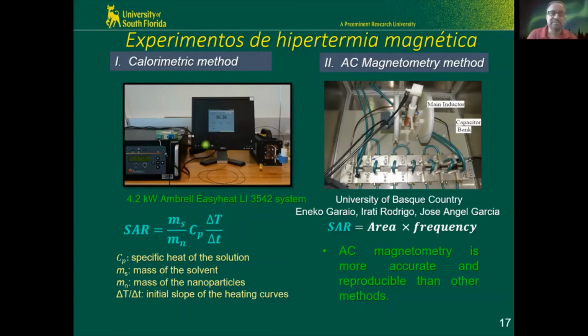And so what we do is that we measure, we have these particles in fluid or any kind of medium here, and we directly measure the temperature using various kinds of thermal sensors. It could be optical, using a laser, we can measure the local temperature. So what we measure here is the rate at which the temperature changes. Keep in mind that we have to heat up the cancer cells to above 40 degrees. So we measure the effectiveness by how fast we can increase the temperature of the nanoparticles.